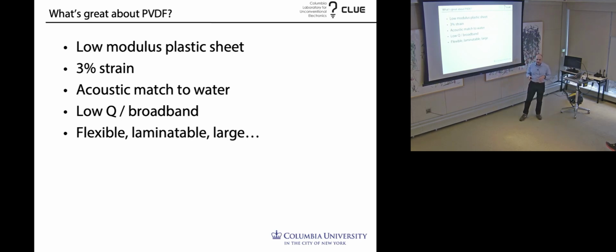A second advantage is that PVDF can also withstand a strain of 3%. And I challenge any ceramic to withstand a strain of greater than 1% without cracking. And so with PVDF, we can apply larger forces, we can have higher impulses, which is nice.